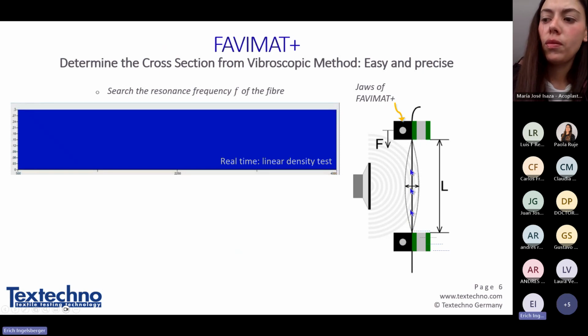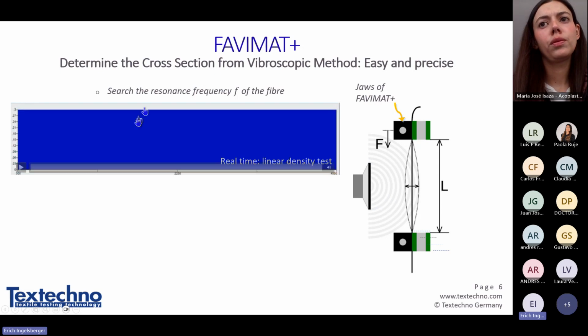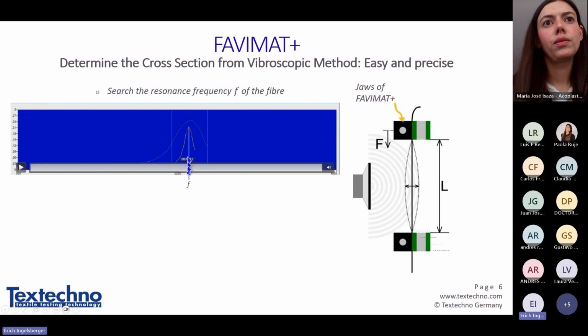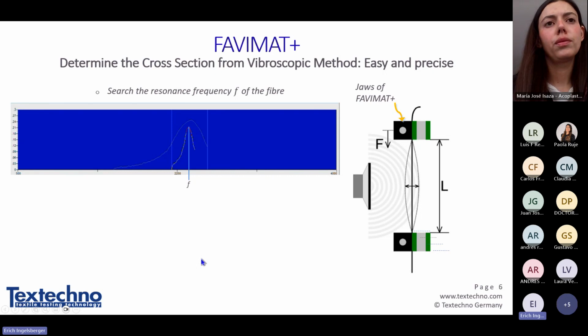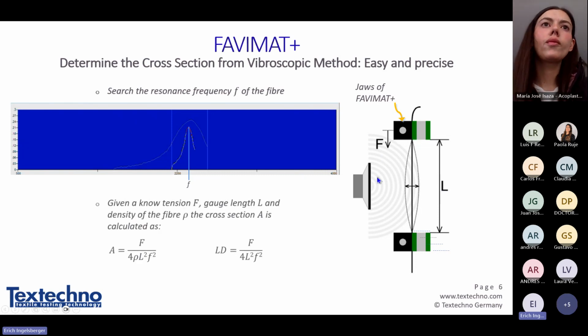When approaching this pretension, we know very precisely, up to 0.1 micronewton precision, the tension of the fiber. We know very precisely the so-called vibrating length of the fiber. With the speaker system here, we apply a sound wave, which you can see on the screen when I start the video - this is the amplitude of the fiber vibration over frequency. We measure the resonance frequency, finding it as the maximum of fiber vibration. From the resonance frequency, the length, and the pretension, we can then calculate the so-called linear density.